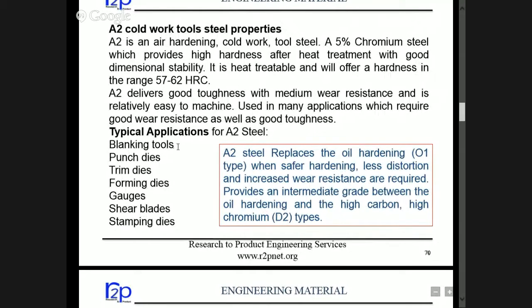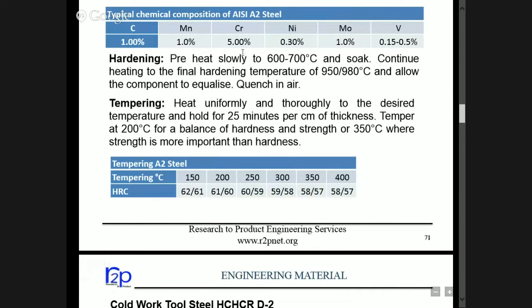And the applications are almost similar, if the number of pieces required is more: blanking, punching, trim, forming dies, gauges, shear blades. So here you can see that some of the alloying elements are more, chromium is more, moly is more. And hardening is done by heating slowly to 600 to 700 degrees centigrade, doing soaking, then taking it to the final hardening temperature 950 to 980 and allowing it to cool. So quenching can be done in air. Tempering is done at a lower temperature, tempered to 200 degrees centigrade for a balance of hardness and toughness.